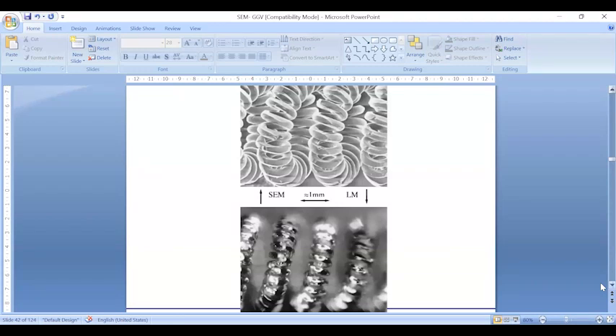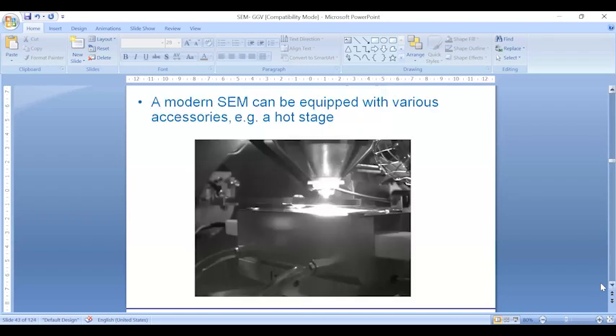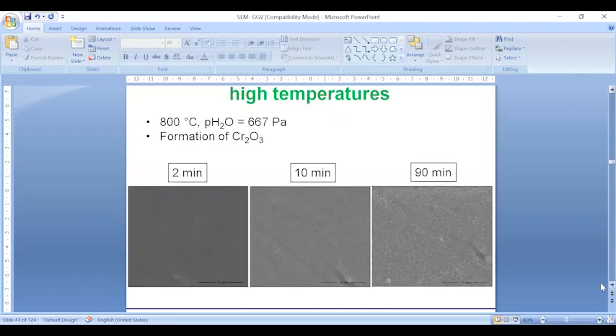This is some coil. This looks like carbon fibers, and the upper image is the scanning electron microscopy. The lower image is the optical microscopy that you can see here. In scanning microscopy we can get the clear information. That is one. This modern SEM equipment with the accessory of the hot stage means we can give some temperature to your sample during the imaging process. This is known as the in situ experiment, in situ process of your system.